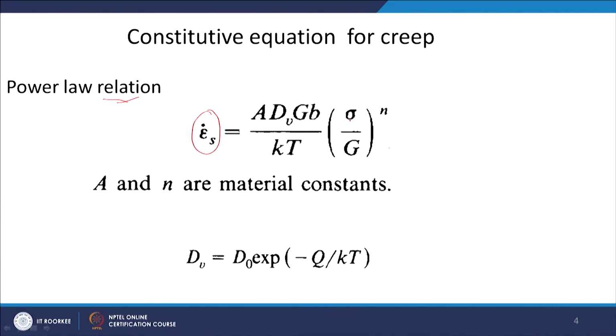So when we are looking at the strain as a function of time, of course we are looking at the strain rate, okay. So under an applied constant load, what is the strain rate of deformation, okay. So we are looking at the strain rate, that is my dependent variable, and this sigma is my independent variable which I am applying, and these are called power law relationships because you have an exponent here over whatever is your input variable, sigma in this case, okay. So you can see that there are some material constants here, for example A and n are material constants, okay.